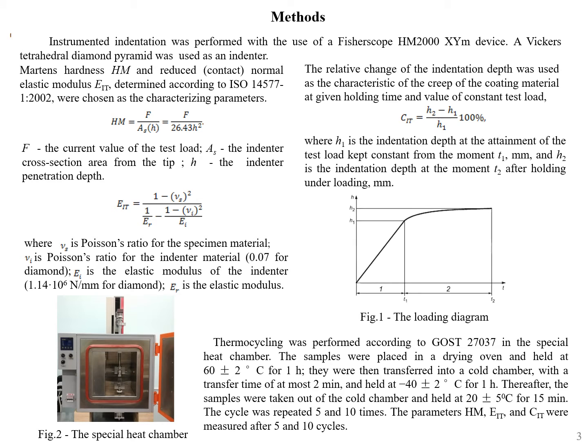Instrumented indentation was performed with the use of a Fischerscope HM2000 XYm device. A Vickers tetrahedral diamond pyramid was used as an indenter. Martens hardness and reduced contact normal elastic modulus were chosen as the characterizing parameters. The relative change of the indentation depth was used as the characteristic of the creep of the coating material at given holding time and value of constant test load.